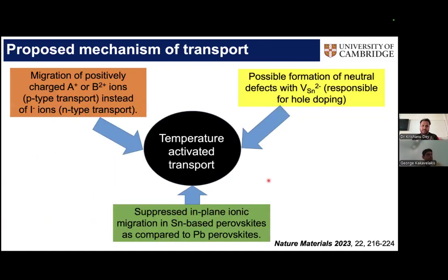So one of the things you might already notice is that in the case of lead-based perovskites, we had an N-type transport. So the ions that could have shielded the voltage are iodide ions, whereas in the case of the tin-based perovskites, because it's a P-type transport, the migration of iodine is not very important, whereas the migration of the positively charged ions is more significant. But again, we know from literature that the positively charged ions tend to move slower than the iodide ions. So that could be one of the things.